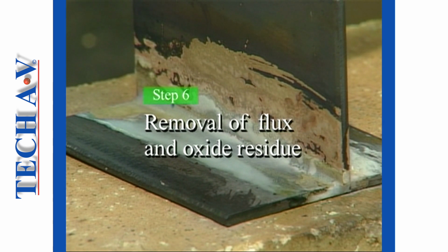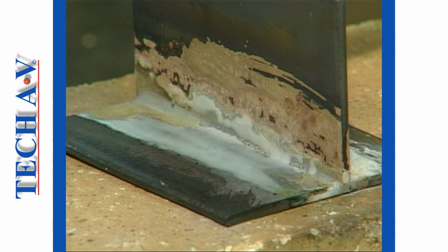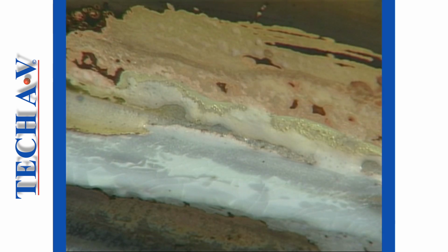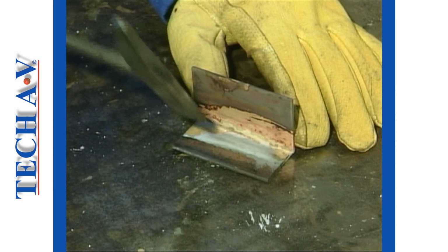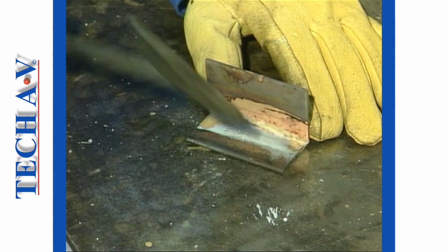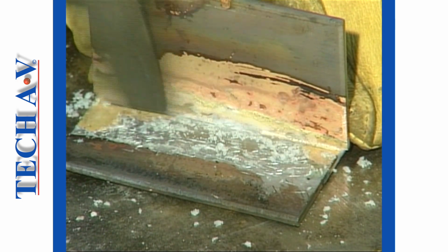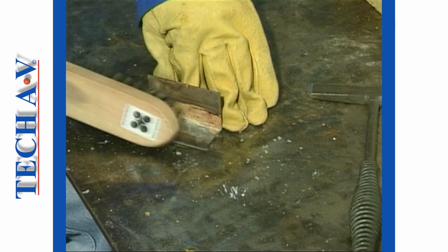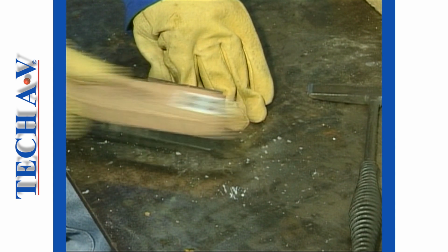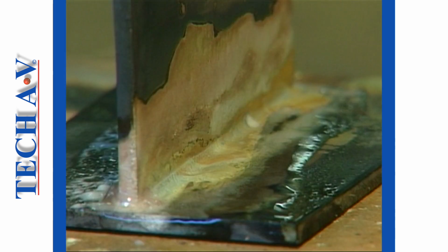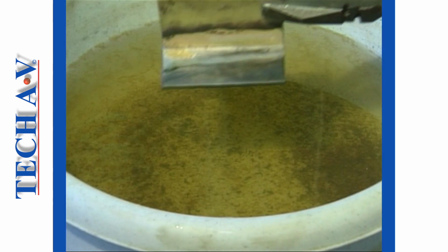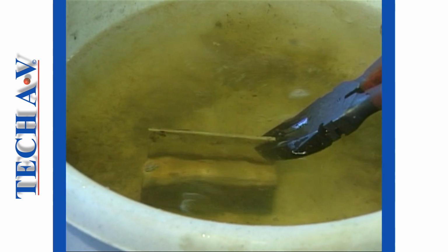After any brazing process involving the use of flux, there will always be an amount of flux residue remaining on the work surfaces. Failure to remove this residue will generally result in corrosion of the metal. If the residue is allowed to cool, then it will become very hard, requiring chipping and hard brushing with a wire brush to remove it. The easiest way to deal with flux residue is, after a short time of air cooling, to quench the work in warm water before the flux has had time to solidify.